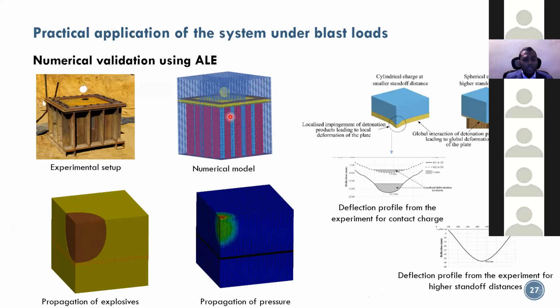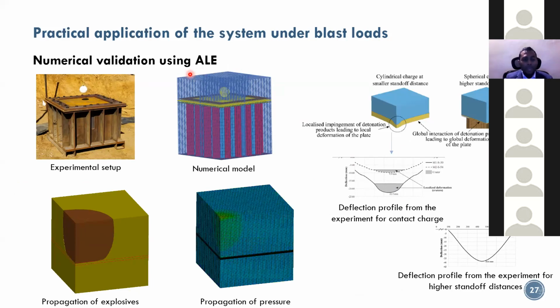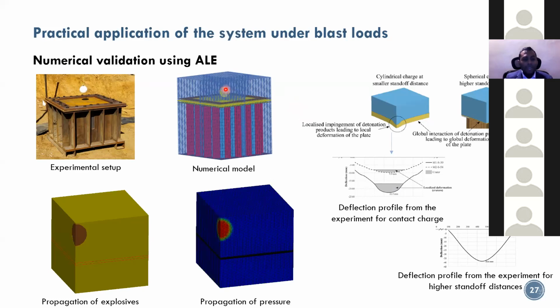So what you see is the blast rig, and it's surrounded by what's called the air domain. And if you can see the little yellow sphere inside, we model it in such a way that we fill this sphere with the explosives and then we allow it to explode. And when that happens, you can see the brown material here expands out and it hits the structure, the red structure.